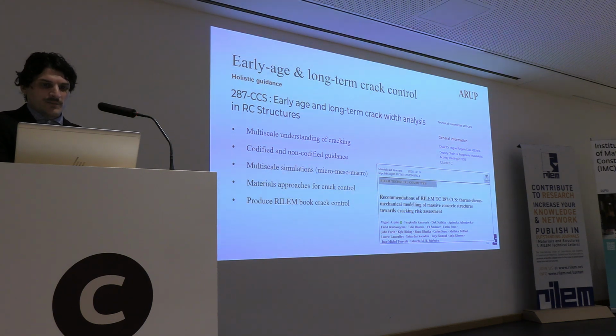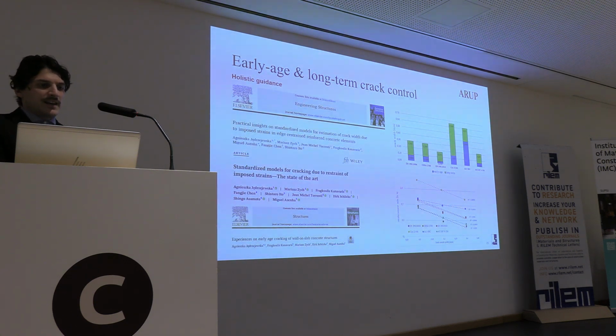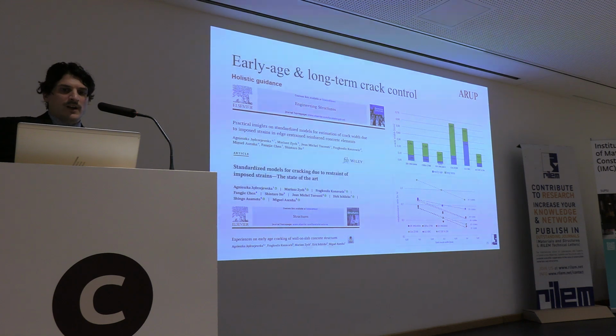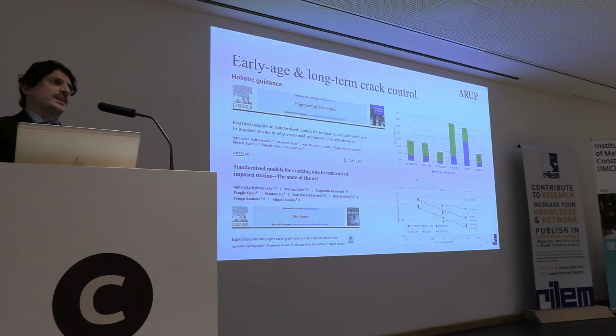So that was quite a big deliverable from the committee, but we also analyzed in depth the models that are being used globally for controlling cracks in concrete. And there's no surprise that we get all these kinds of cracking problems in the world because for a given crack width, different provisions, different codes provide different recommendations for reinforcement. So which one is the correct one? And we are faced with a big problem because controlling crack widths is very well related to the reinforcement quantity. If you want to control the crack width, you have to add more reinforcement. If you have more stringent, more onerous crack widths, you need to add more reinforcement. And it's not just Portland cement and structural concrete that is a carbon contributor, it's also reinforcement. So that's a combination of materials and structures there.